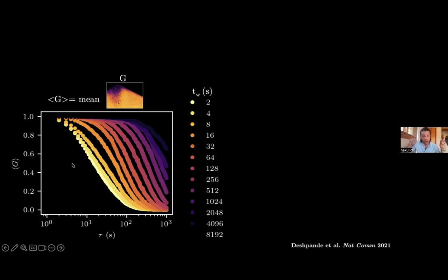And what you can see for the young sand pile, where the waiting time or the age is low, on the order of seconds, there is a quite quick decay. So on this y-axis is the correlation, it's just the measure of similarity. And then on your x-axis is a lag time that's telling you the time at which you're comparing the two speckle images. So this decay is very fast, which means that I lose resemblance very quickly. And that's because my sand pile is creeping more quickly at 2 seconds after the pile has been poured, as opposed to 8,000 seconds or about 2 hours after the pile has been poured.